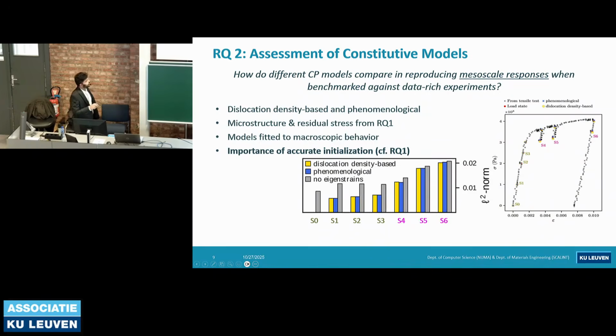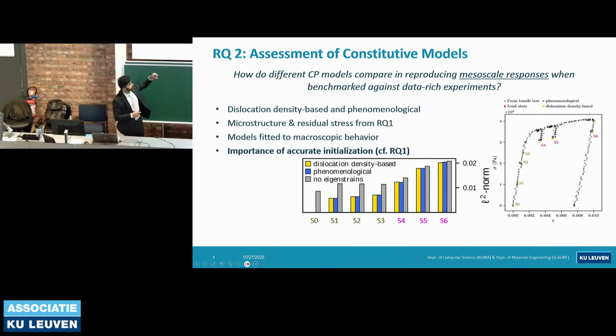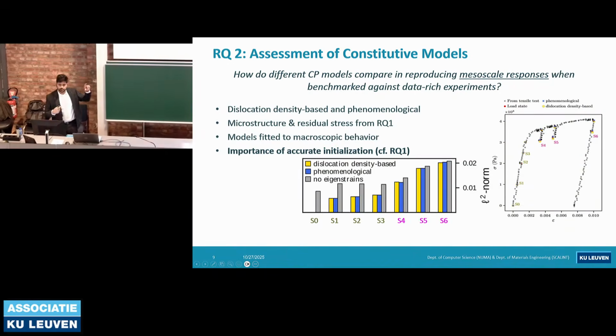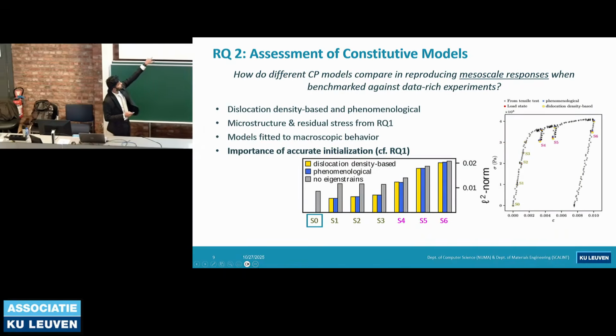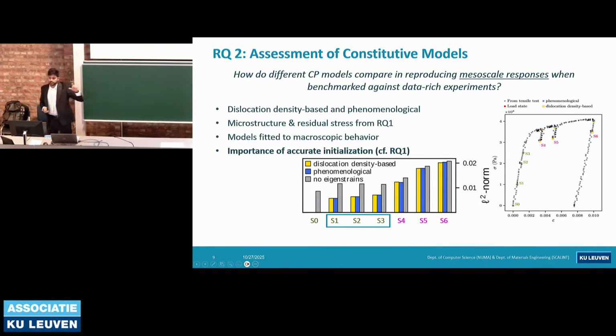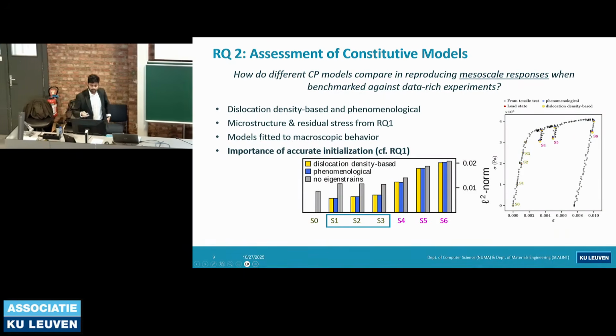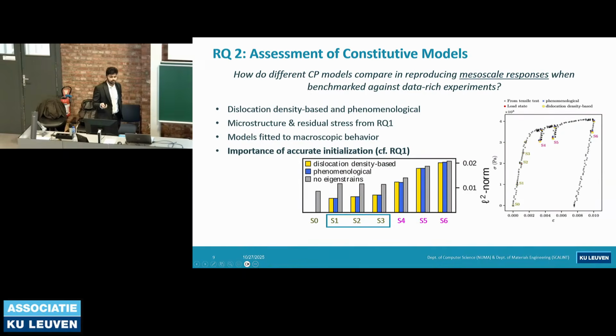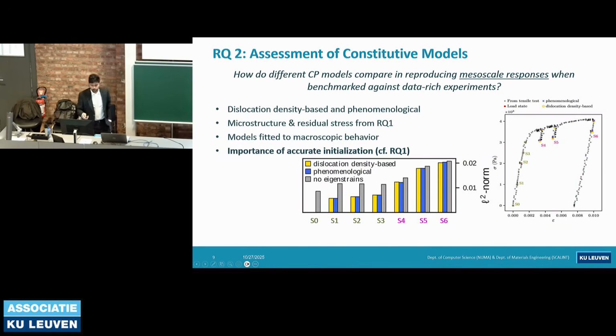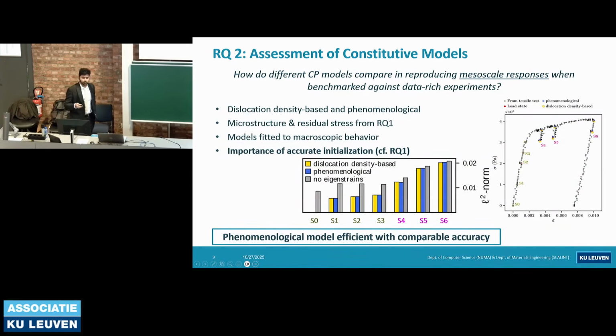So I want you to just focus on these gray lines, which show the scenario where residual stresses were not initialized in the material. As you can see here, on the y-axis, the height of the bar shows the modeling error, and without initializing residual stresses, across the different load states, you see that the value is high. So modeling error is quite high. This again emphasizes the importance of correctly initializing the residual stress states. And then comparing the two different models, dislocation density based and phenomenological, they show comparable accuracy. So with this, the phenomenological model, although being operationally quite efficient with a smaller number of parameters, showed comparable accuracy as the detailed dislocation density based model.